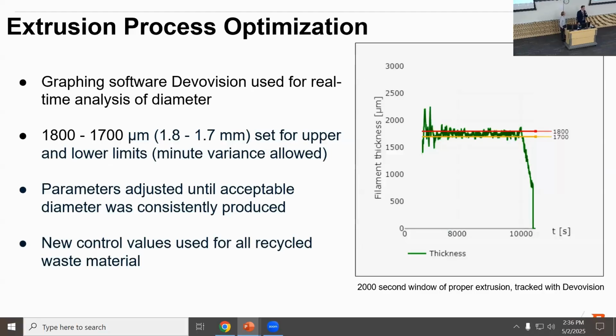To help us with this process, we downloaded some software called DevoVision that 3Devo offered, and this tracked the diameter of the filament in real time. Once we did this, we set some higher and lower limits, about 1.8 to 1.7 millimeters. This was actually a stricter tolerance than the default for DevoVision when you first download it, so we allowed ourselves a bit of leeway if it went a little bit above or below. Essentially, we just adjusted the heaters and the speeds of the screw and the puller to get to a point where we were consistently producing filament that was 1.75 millimeter diameter, and all the parameters were in check. Going forward, this set of parameters was used for all the new waste material. The image on your right is about a 33-minute window of proper extrusion. We spent a lot of time doing this, months trying to get all these parameters correct.